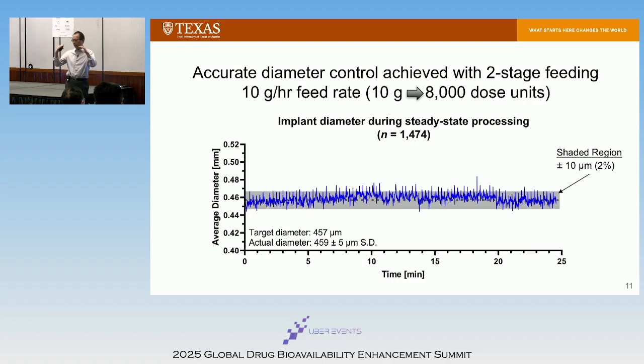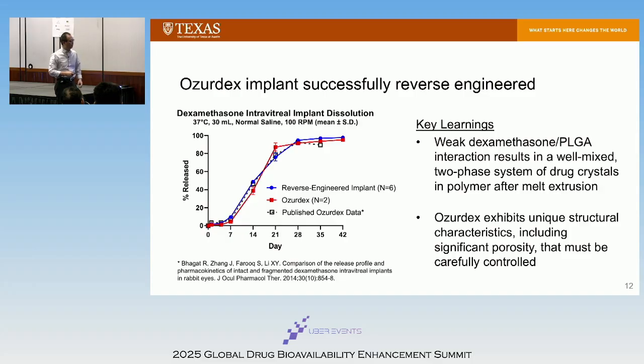So the feed rate is mainly controlled by the RPM of the Haake Mini Lab. But we have another step using the twin screw to feed, to have a little bit of choking effect. But we can get very precise control. And we have shown different graduate students, different days. We don't really try to do it when it's too humid. Okay, but it's actually very consistent. And this actually matched up with published data on Ozurdex. So Ozurdex, and this is actually done in normal saline.